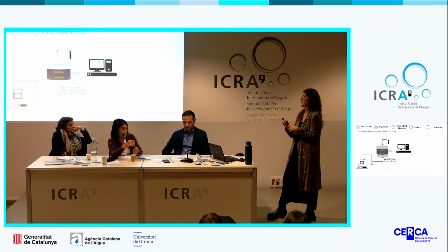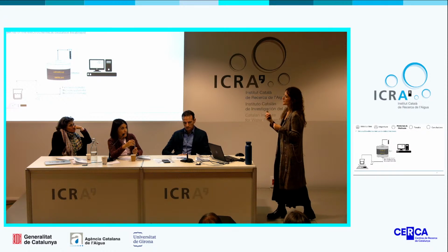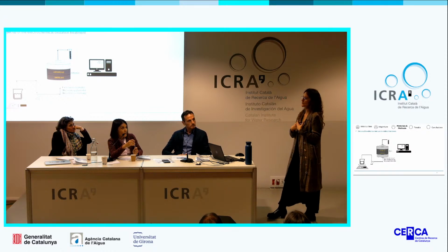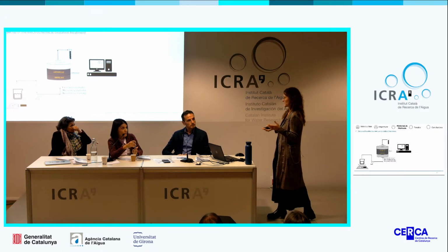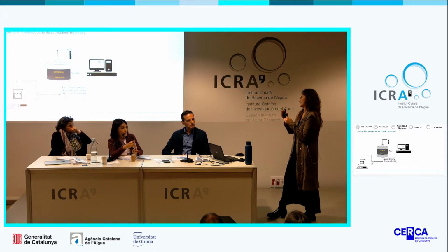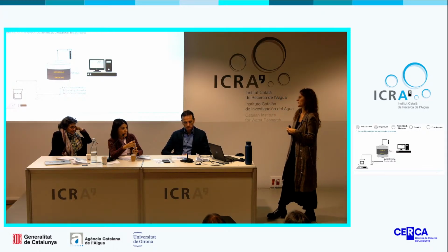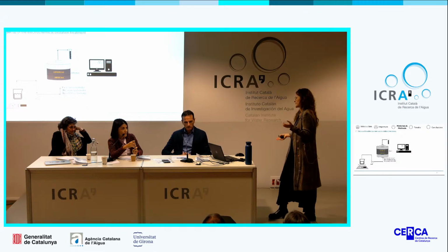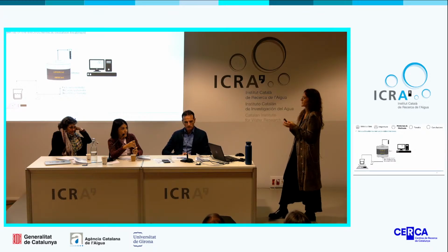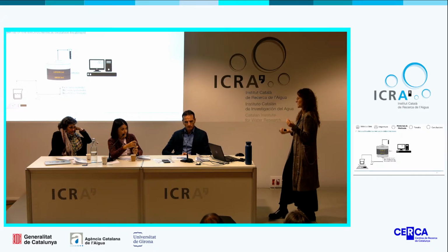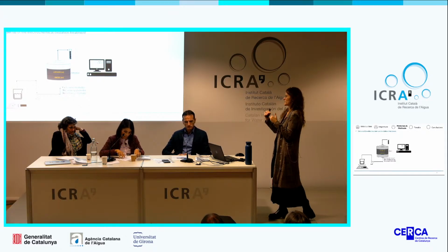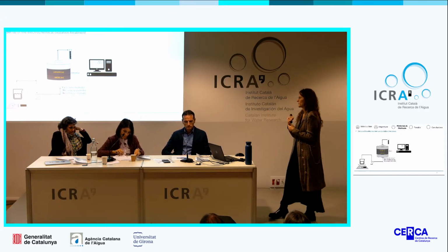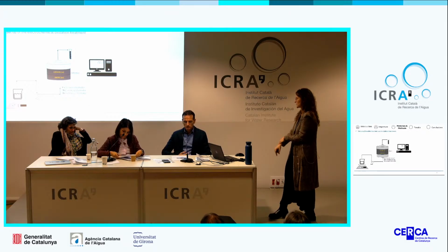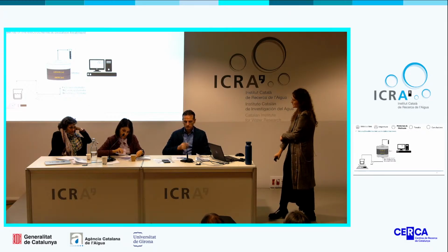But for example, in the experiments that we perform using the sponge, we were partially saturated. We didn't get these steady state conditions because the sponge was partially saturated, but in this case we were just evaluating the impact of the current. But usually, yes, we work in a steady state condition when we apply the current.